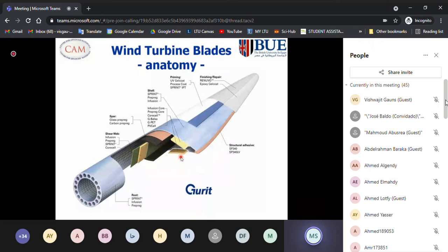And then there is one critical element, and actually most of the failures in blades occur at this location, which is the adhesive joint between the two halves of the blade. Now, when we go into the fabrication process, you will see that whenever we produce a blade, we produce the upper shell and lower shell separately, and then we join them using structural adhesive. And if you have any problem with the structural adhesive, then the failure will initiate at this location.